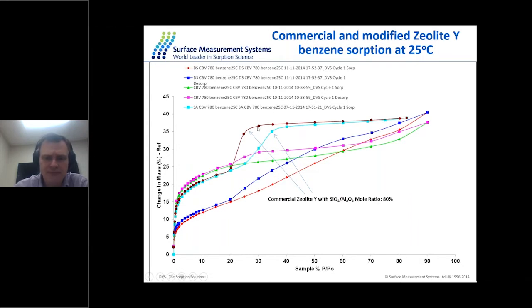So where is... this is the commercial zeolite Y. So what you see, you get quite lots of porosity, and you have the microporous and mesoporous parts in this zeolite. So it's a mixture of both.